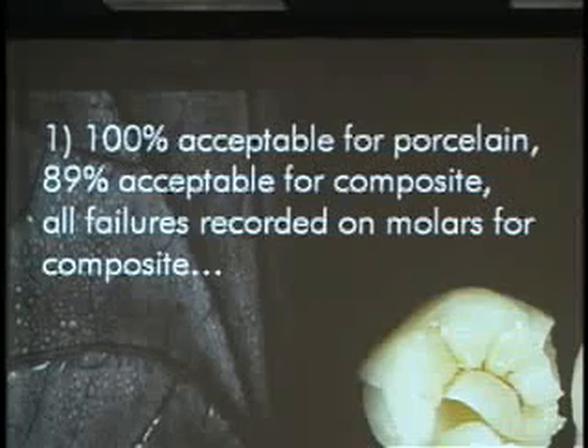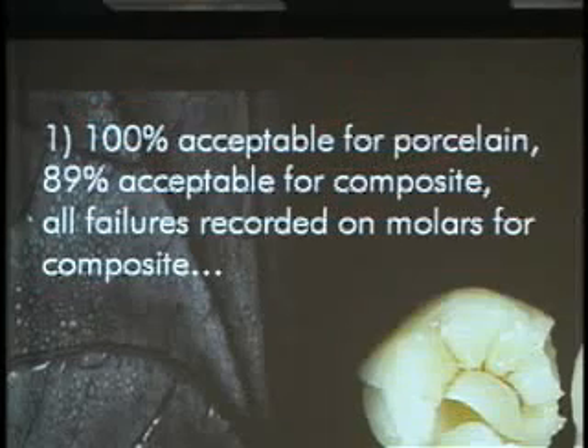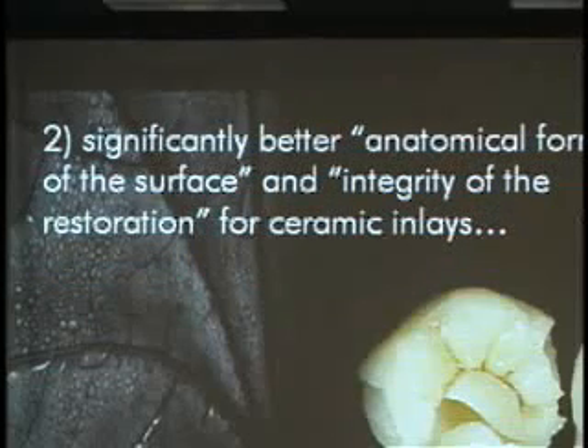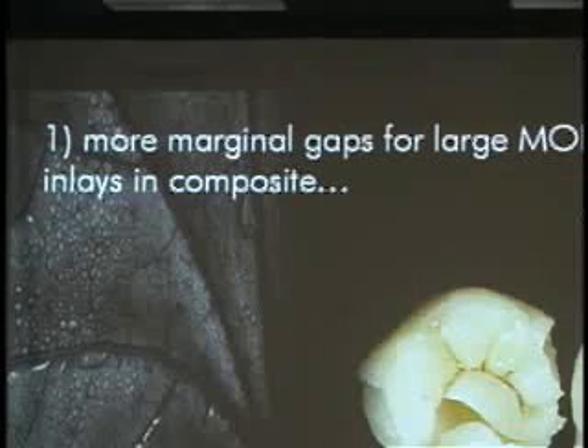This is another study now. It's a clinical study, 3 years. It's very short, and using USPHS criteria, 100% of acceptable porcelain restorations versus 89% for composites. Basically what comes out from this study is that failure is more likely to occur on molars, whether you use composite or porcelain. And also from this study, significantly better anatomical form of the surface and integrity of the restoration for ceramic inlays. Maybe, I don't know if you agree on that one. There is not much data on that. This is one study, and I think we need much more data to show these differences.